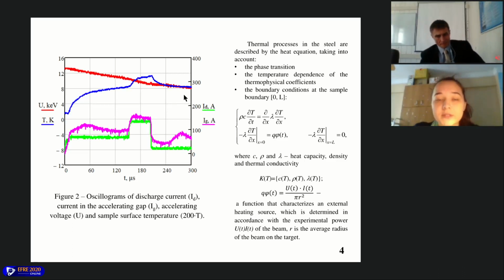So the main purpose of the study was to conduct a numerical simulation of thermal processes happening in the surface layer of different materials. In order to conduct it, we have to solve a heat equation, which takes into account three main points. The first one is the phase transition. The second one is the temperature dependence of the thermophysical coefficients, and also the boundary conditions at the sample boundary presented on the slide. Also, on the slide, you may see a function that characterizes an external heating source, which is determined in accordance with the experimental power.